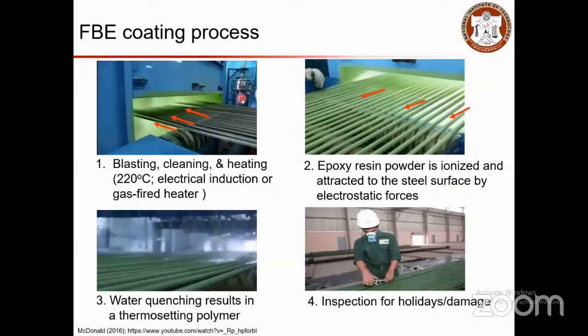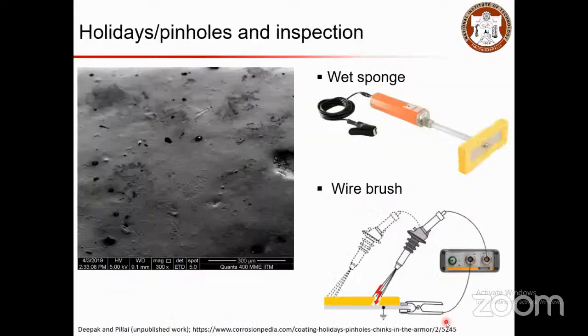So how is it being coated? So it's a blasting process. So once you get your rebar, epoxy resin powder is ionized and attracted to the steel surface by electrostatic force. Then you do water quenching in a thermosetting polymer, and then you do inspection. So here this person is doing inspection for holiday or damage. So holiday is not the holiday that we usually take. It is the name that is given to the pinholes or micro damages. So that need to be inspected. So for a certain length, you have some allowable limit of the holidays or damage, that is less than 1.1% or something. So if it is more, then that is going to accelerate the behavior for the corrosion in a negative way.